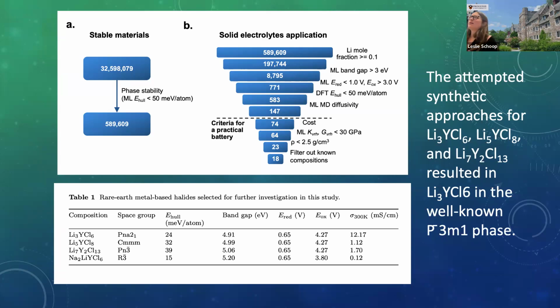The problem of disorder is also a problem here. So all these targets resulted in this material, and that is actually a well-known lithium-ion conductor. So that's known, it's studied, people know it's a good lithium-ion conductor. So then they thought, damn it, we found one material we already know, how do we save this paper? So they're like, oh, let's dope the lithium with some sodium. So they also made the chemical connection.